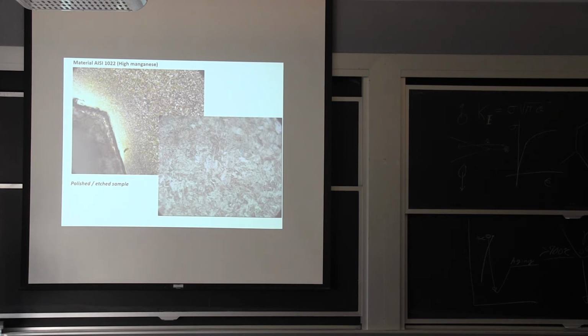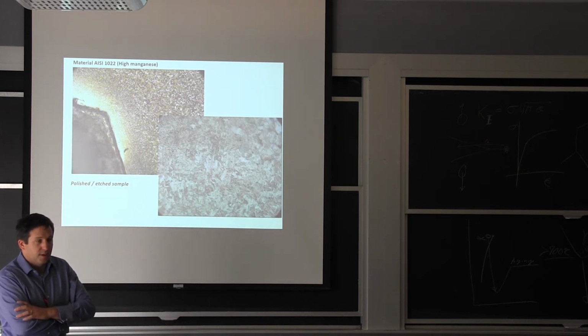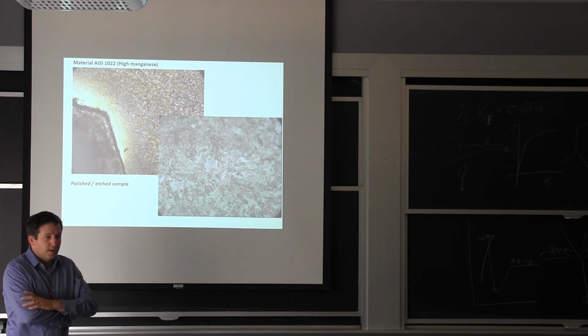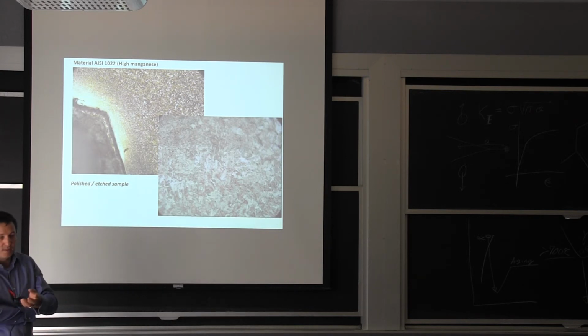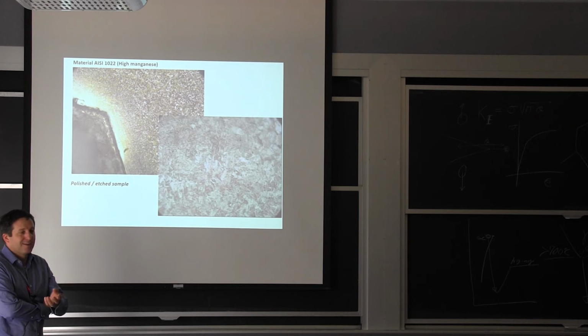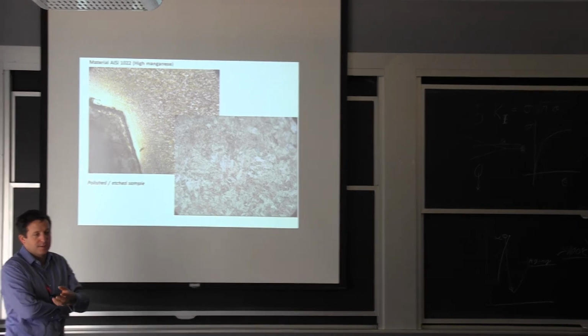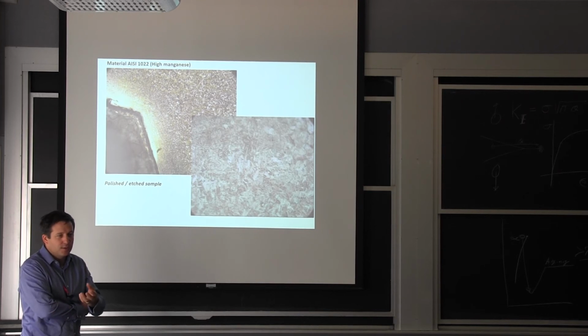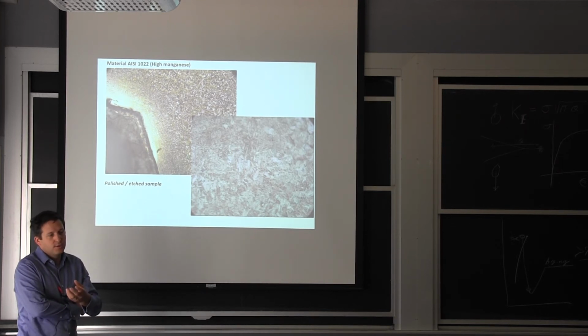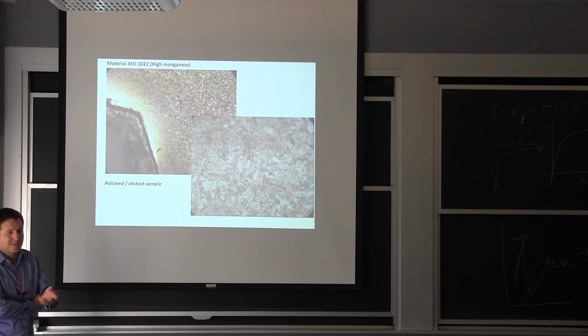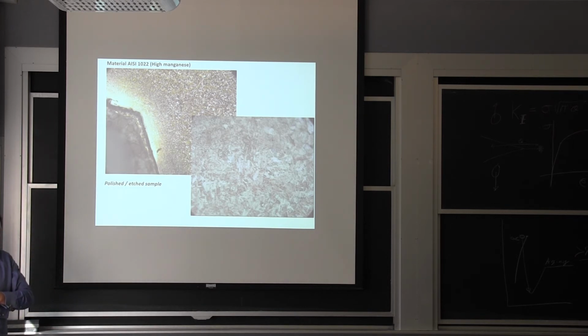Yes? Wouldn't higher carbon content of the martensite make it more brittle? Yes, it does. And that's kind of what we're looking for in the bit. It's brittle, but if you're thinking about drilling, it means one material is going to act as if it was diamond or carbides. You don't want it to deform at all. So you're looking for a difference in the hardness that's something of the order of 50% harder. So it remains elastic in that process.